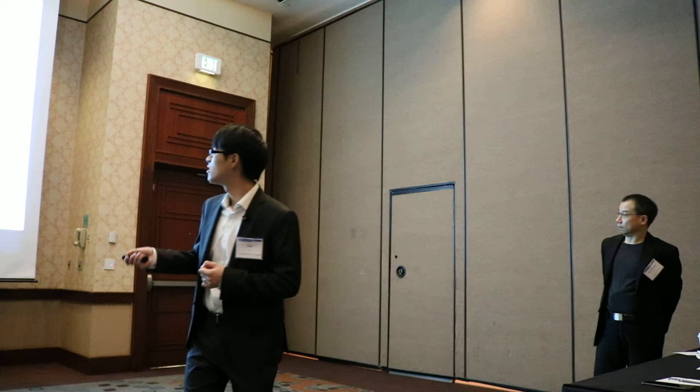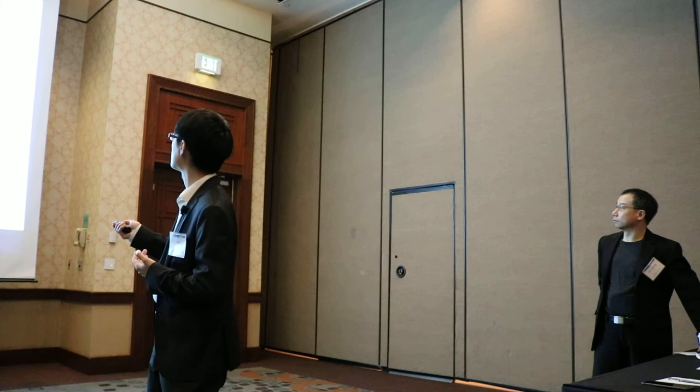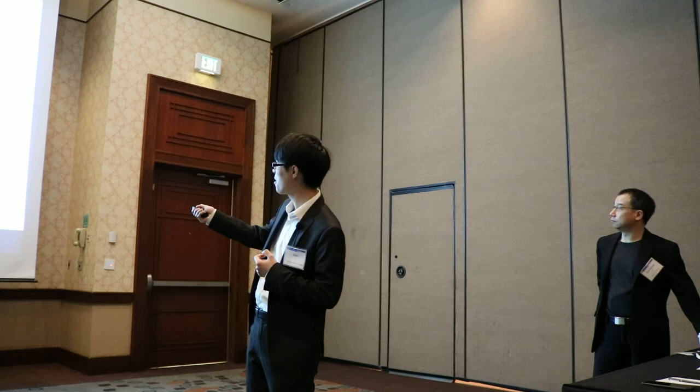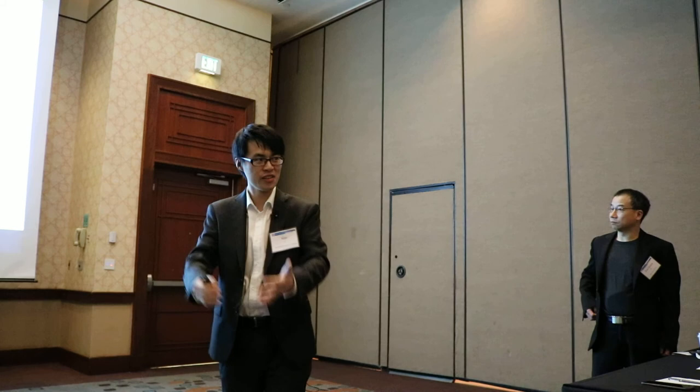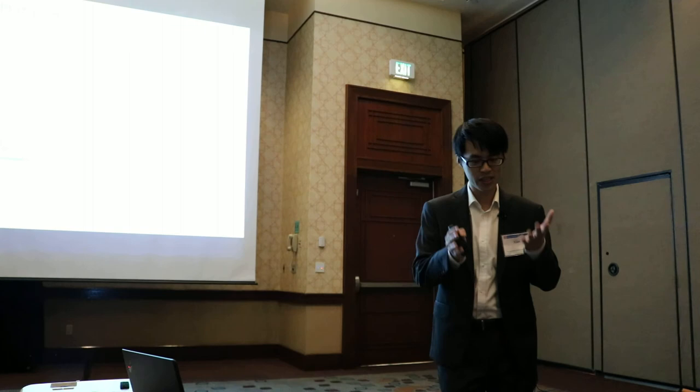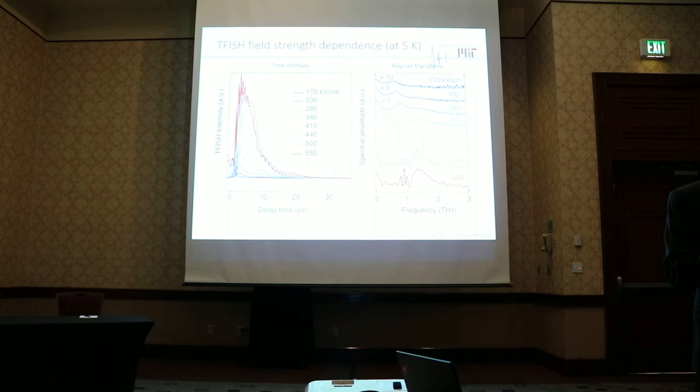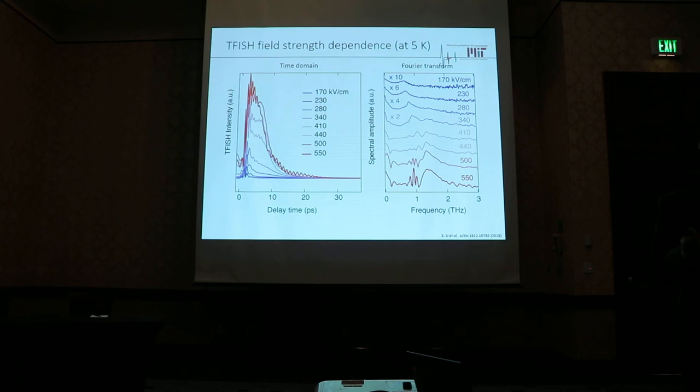We realize multiple things are happening at the same time in the experiment. It's kind of clear from the experiment that when we increase the terahertz field strength, the peak actually moves — the phonon spectrum blue-shifts. That complicates things. Also, when you induce the ferroelectric phase transition, the modes can actually split, because two of the modes are doubly degenerate. So they split, and after they split, they can actually harden very quickly. Therefore it's kind of hard to determine which mode is which exactly.